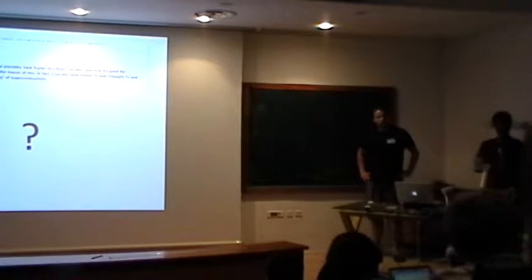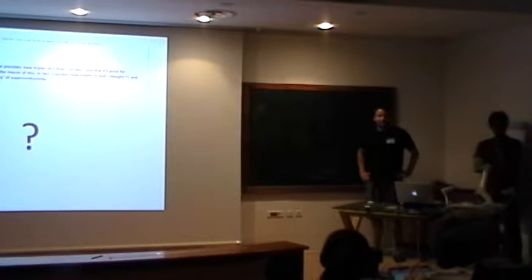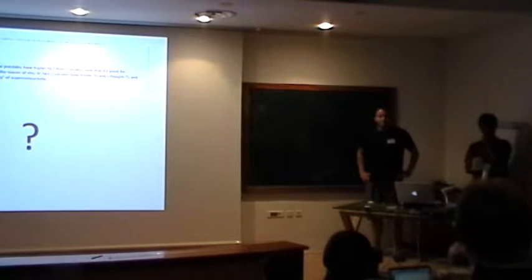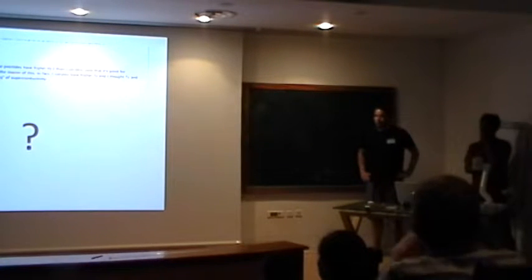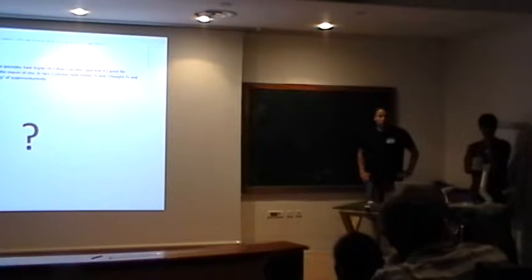Well, actually, the main problem is grain boundaries for the practical guys. They only care about grain boundaries. That is why magnesium diboride is very good for us. Very boring for theorists, but very good for making wires because the grain boundaries are not so killing. And as far as I know, grain boundaries are a big problem in the labs, because of sample growth, or for making wires. If grain boundaries are destructive, you have to make a wire that's a single crystal, and that's kind of problematic.